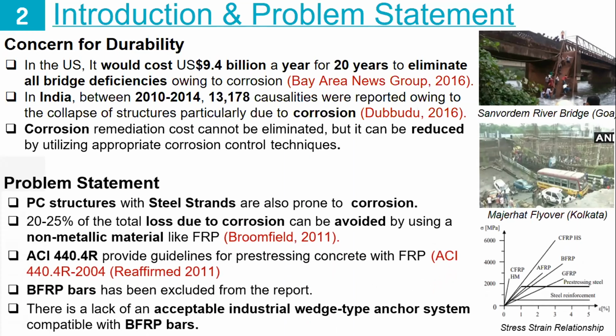However, we have noticed that even when we pre-stress concrete structures, the pre-stressing element is made of steel, which is prone to corrosion. Hence, the problem of corrosion still persists in pre-stressed concrete structures. So we can see that 20 to 25% of the total loss due to corrosion can be avoided by using non-metallic pre-stressing elements like FRP. And it is becoming more and more common every day, because even the ACI 440 code has given guidelines for pre-stressing of concrete structures using FRP elements.